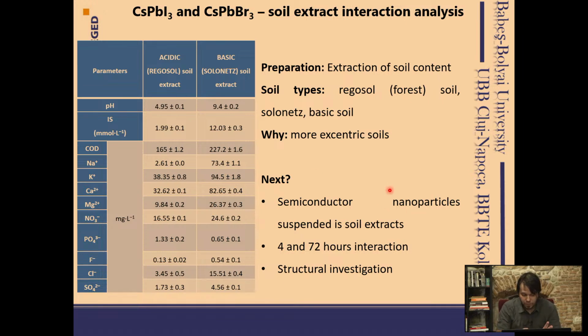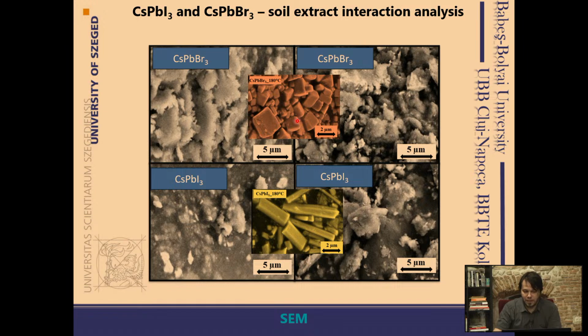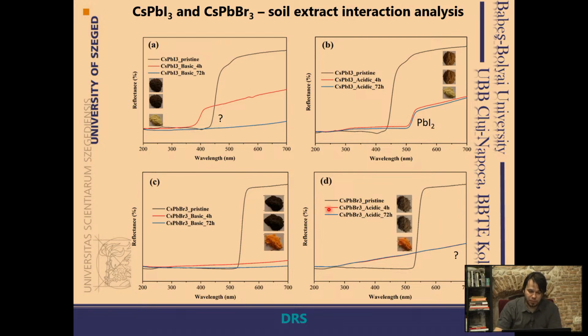And we have found that all the solutions which we investigated had lead in them, which is not a beneficial thing to have. Usually lead is quite toxic and it is a heavy metal. And think about it, these are 4 and 72 hours investigations. If we go back and see the electron microscopic figures, we will see the original nanoparticles, and then after coming in contact with the soil extract. If you still have a little problem imagining the soil extract, you can imagine a soil which is irrigated by rain. So a soil extract can be in fact rain interacting with your soil. So if these nanoparticles are in the soil in any kind of concentration and it is raining, then these materials will slowly transform into something else. And this was also supported by our analysis of the color of these materials.